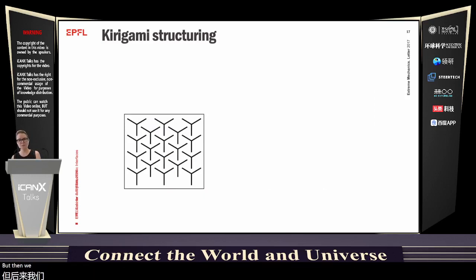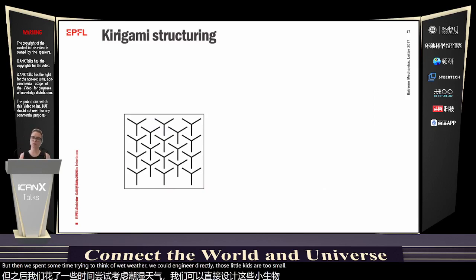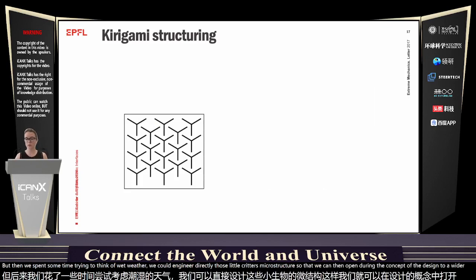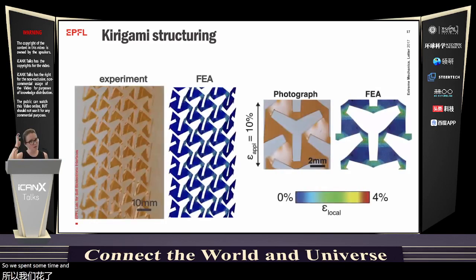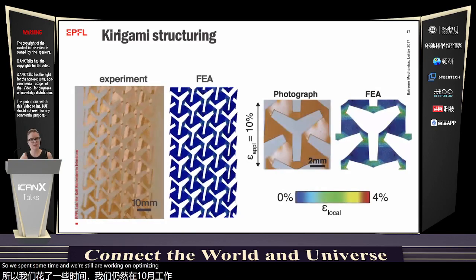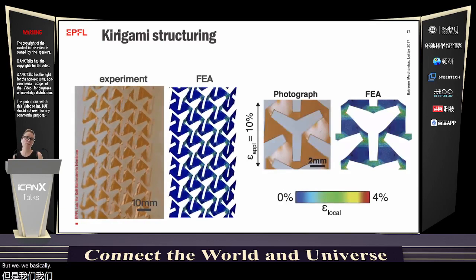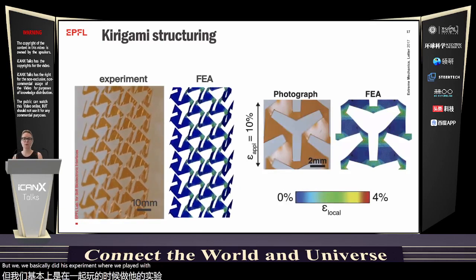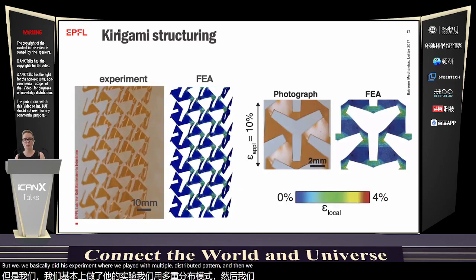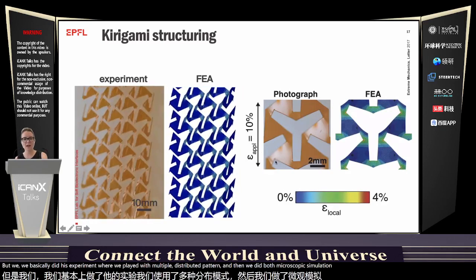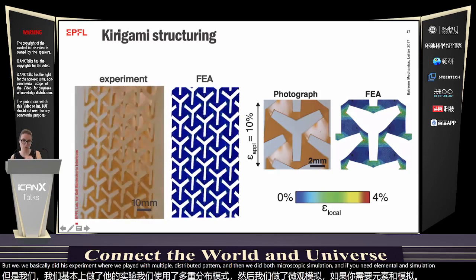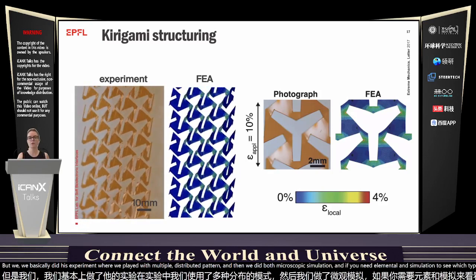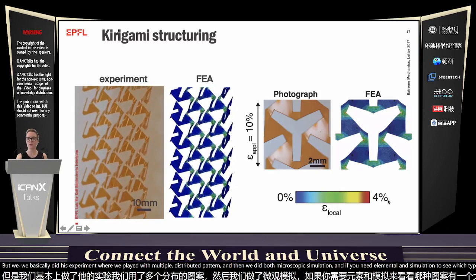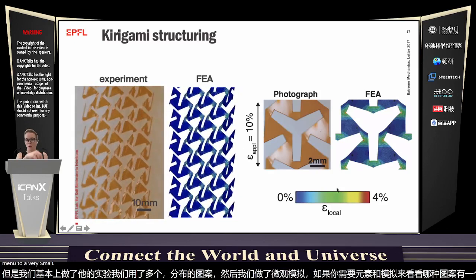But then we spent some time trying to think of whether we could engineer directly those little cuts or those microstructures so that we can then open the concept or the design to a wider range of material. So we spent some time and we still are working on optimizing this further. But we basically did this experiment where we played with multiple distributed patterns, and then we did both macroscopic simulation and finite element simulation to see which type of pattern would allow to have a macroscopic deformation with a minute or very small residual strain in the structure.